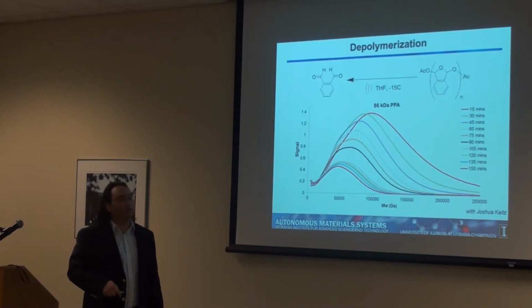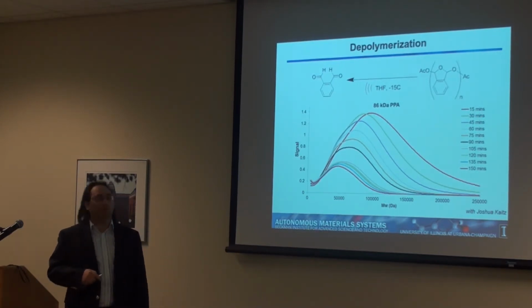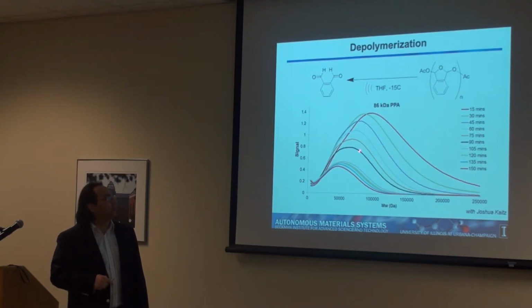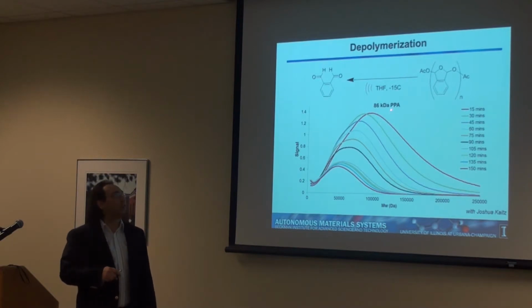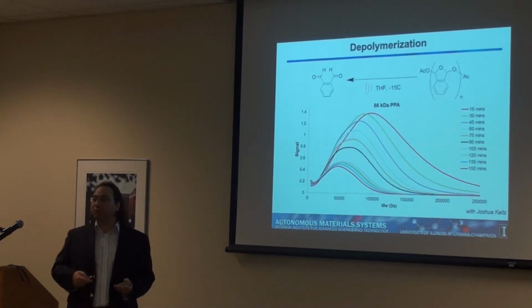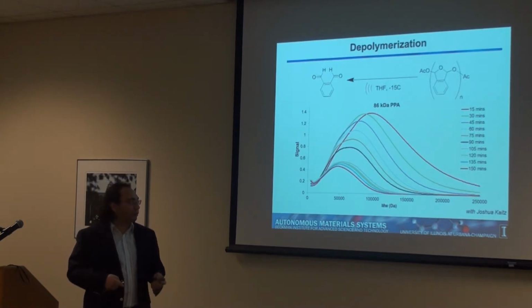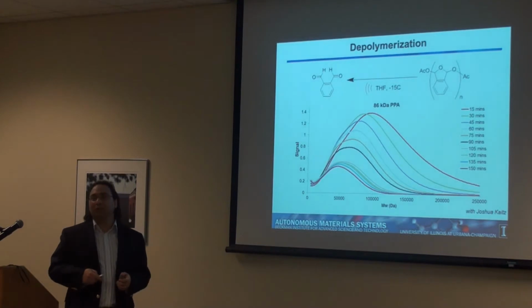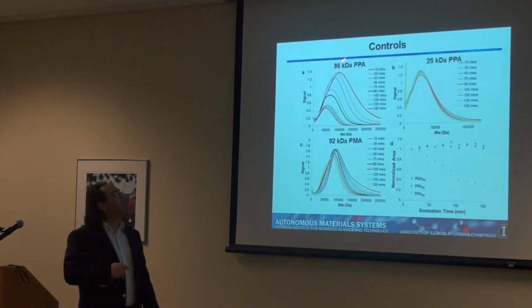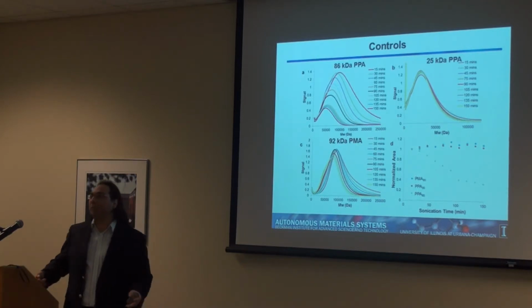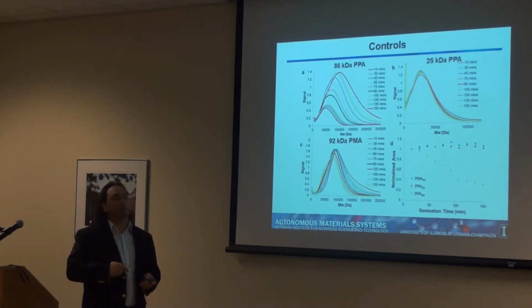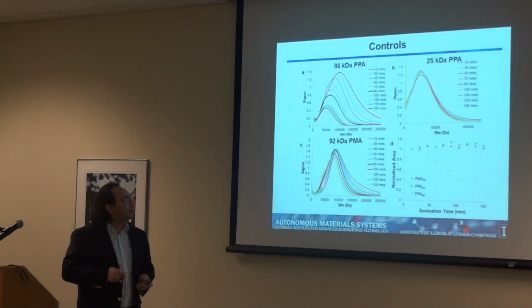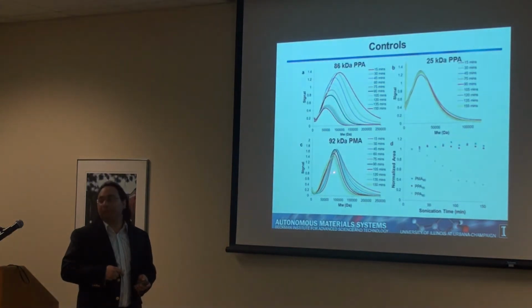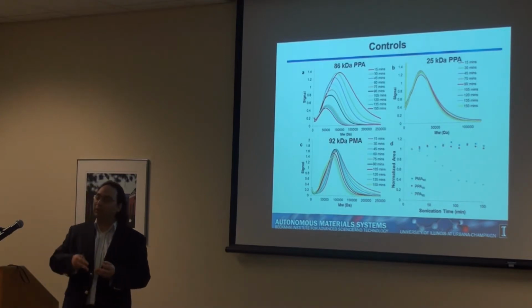if you just do the reaction over time, applying mechanical force by ultrasonication, you see that the peak area of the polymer starts going down at the same concentration. So basically what you see is that the polymer concentration is going down. The polymer is completely disappearing. This is very nice, but obviously you need controls to prove that this is being done by mechanical force. So, for example, if you take a different polymer that does not undergo depolymerization, such as polymethyl acrylate, and you apply mechanical force, you see that there is also a change. This peak starts going down. On the other hand, a peak at around half the molecular weight starts going up, which is what you expect when you take a polymer and break it in two.